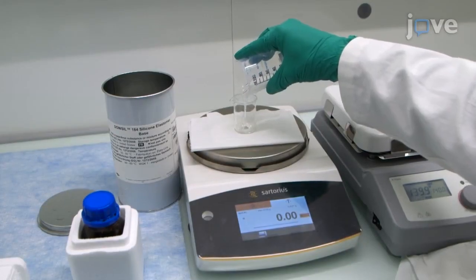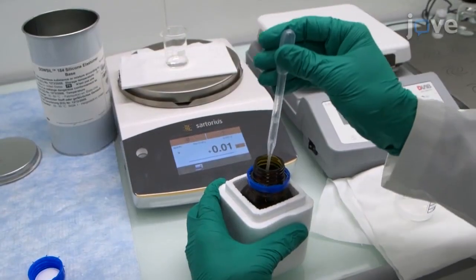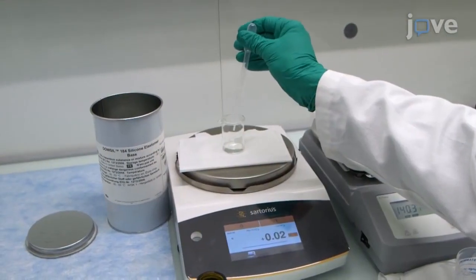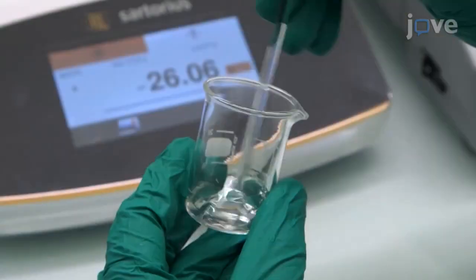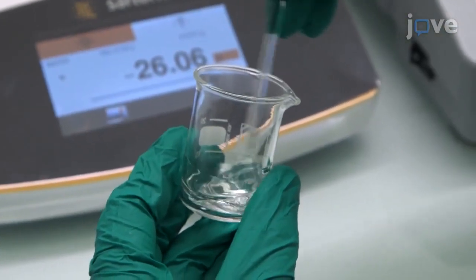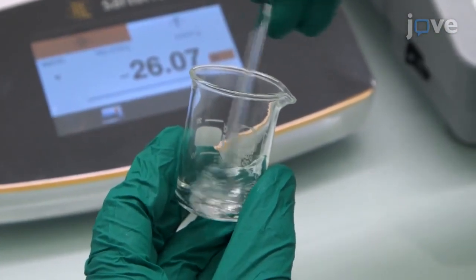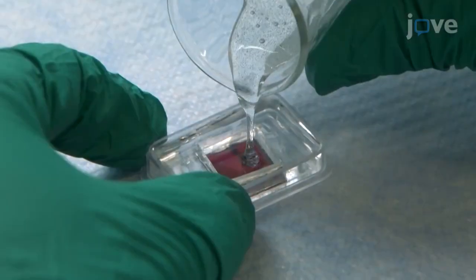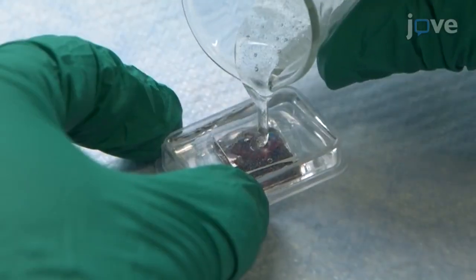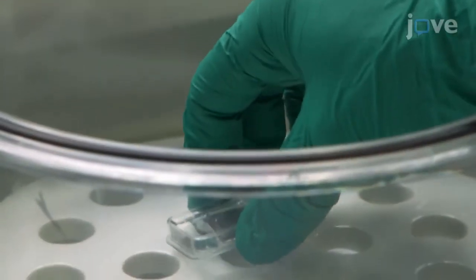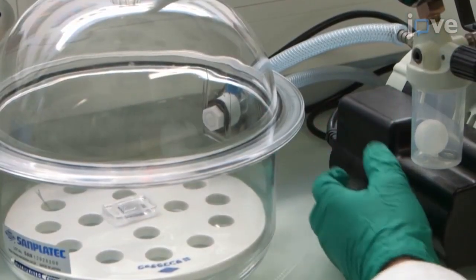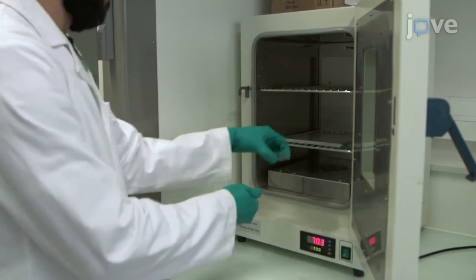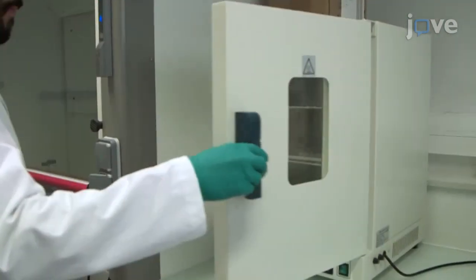Begin by mixing 1 part of the curing agent with 10 parts of elastomer in a beaker on the balance. Stir this mixture with a glass stick until a homogeneous distribution of air bubbles is obtained. Then fill the master with PDMS and remove the bubbles in a vacuum chamber. Introduce the PDMS and silicon master into a stove at 70 degrees Celsius for 2 hours.